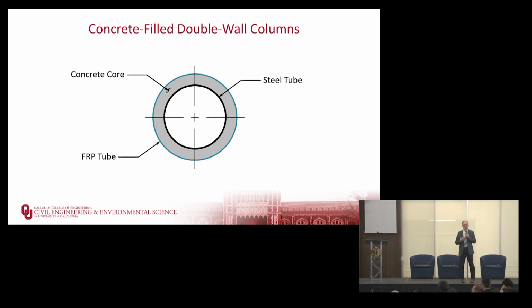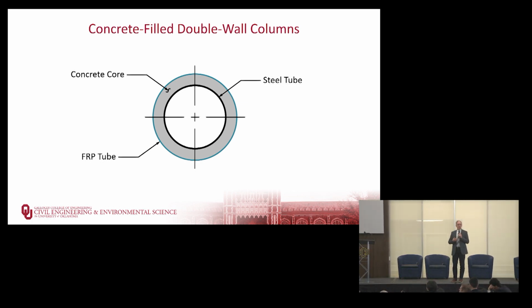The FRP tube acts as a stay-in-place form. It also provides resistance to chlorides and other deleterious materials. The concrete core gives a lot of compressive strength, but also braces the FRP tube and the inner steel tube. And then the inner steel tube and the FRP tube provide confinement to the concrete, which increases its apparent strength. And then the steel provides the ductility and the flexural resistance for the column.